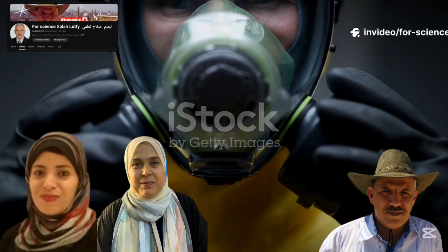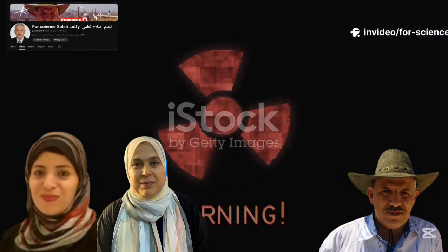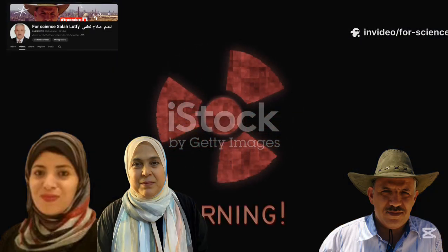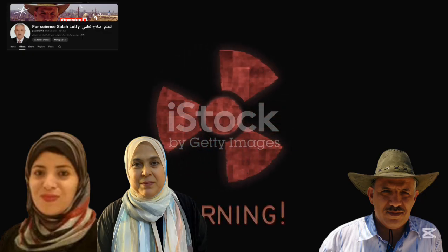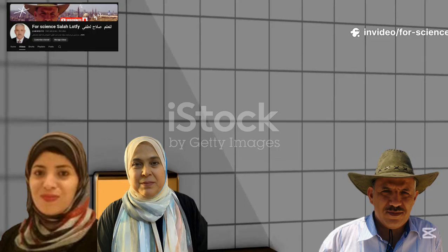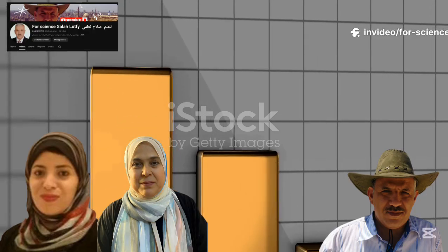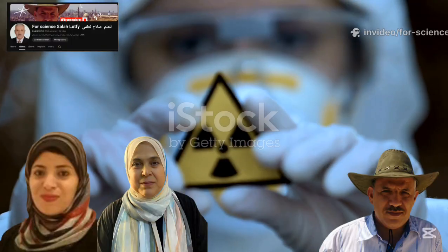The researchers calculated the excess lifetime cancer risk for workers exposed 2,000 hours per year over 40 years. Results showed G1 reduced lifetime cancer risk the most, outperforming many previously studied shielding glasses. G2 and G3 were less effective than G1, but still better than other common glass shields like ZB and BI-10. This underscores the direct health and safety benefits of these advanced materials.